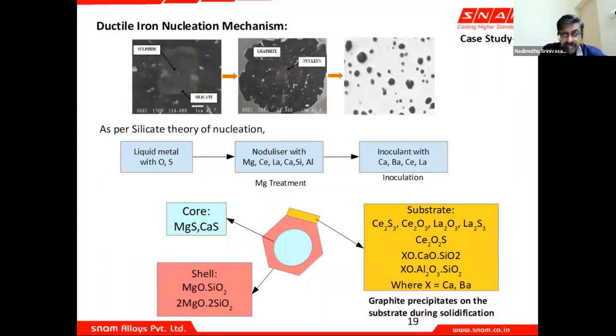Just to explain the ductile iron mechanism to you, there are a lot of theories, and what I'm going to present to you is the latest theory. We had the gas bubble theory, the oxysulfide theory, and this is called the silicate theory. Each of the earlier theories was disputed, and this theory came in after we had the scanning electron microscope, where they could see the nodules very well, and the nuclei and the core of the nuclei. Based on this theory, all the alloy developments are now taking place. The core of this nucleus is a magnesium sulfide and a calcium sulfide or cerium sulfide. The shell is MgO·SiO2 or 2MgO·SiO2.